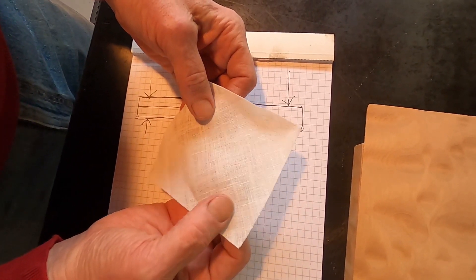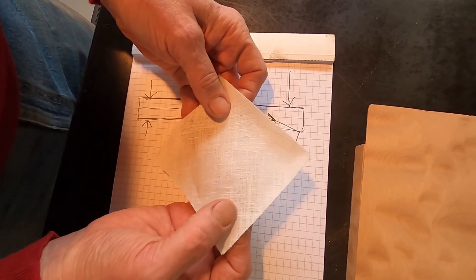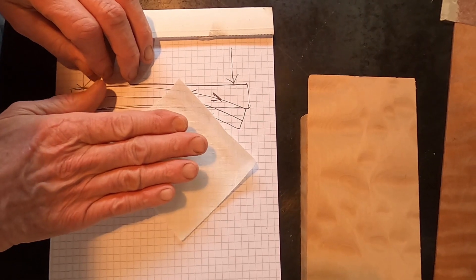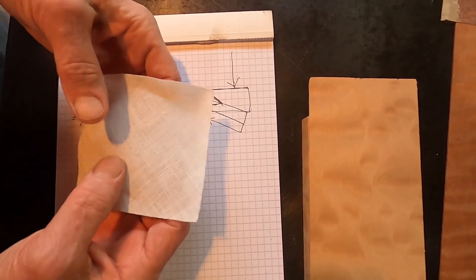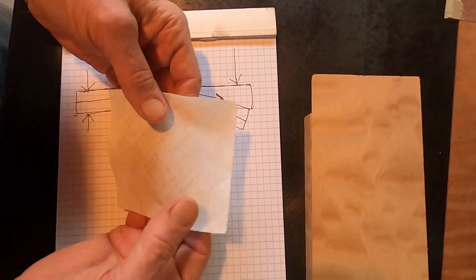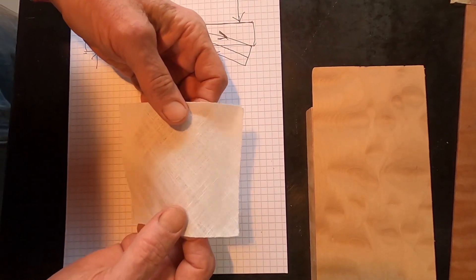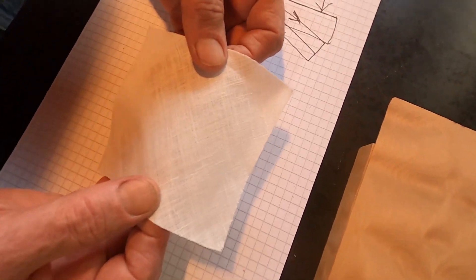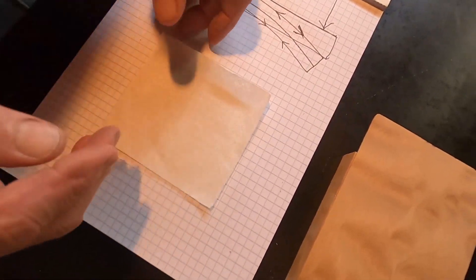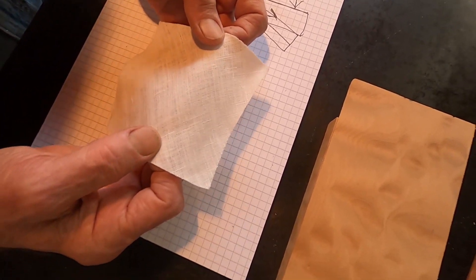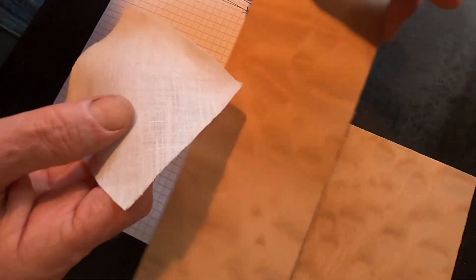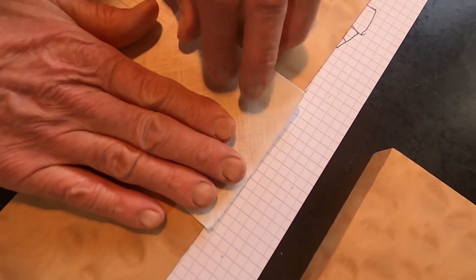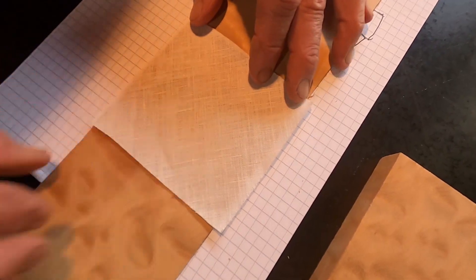And this is an example of the material that I like. This is what they call handkerchief linen, and it's about nine thousandths thick, nine thousandths of an inch. And it's a plain weave. In other words, there's pretty much the same number of fibers going in both the warp and the weft direction, and so it's a balanced cloth. But as you can see, the way I use it, I deliberately cut it out on the bias, or 45 degrees, so that it's crossways to the fibers in the wood, plus or minus 45 we call it. And fiber orientation is always important in guitar making or any kind of woodworking. And now that we're trying to support the material while we bend it, we're going to have support coming in both these diagonal directions.